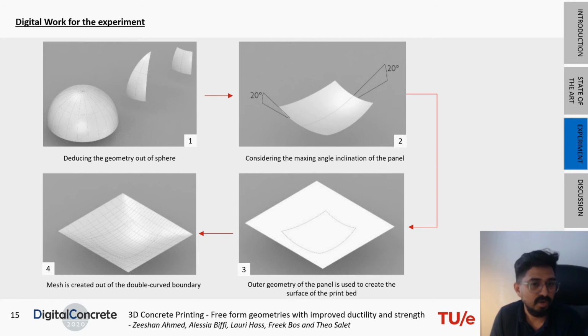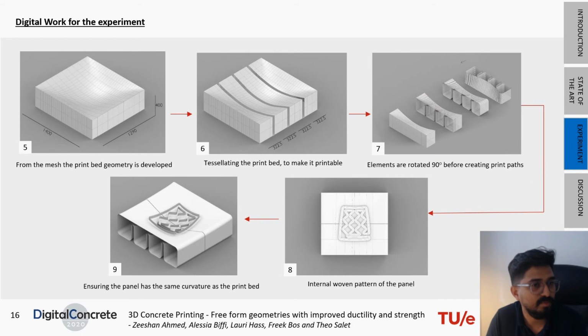Moving on, the outline of this panel was used to create the surface of the print bed, and the boundary surface was created by using a mesh. Finally, from the mesh, the print bed geometry was developed. To make the print bed, it was tessellated into 4 parts, and each of these parts was rotated 90 degrees before making the print paths for this printing process. Simultaneously, an internal woven pattern was developed to give more internal structure to the panel, and finally, both the panel and the print bed were checked to ensure they have the same curvature.